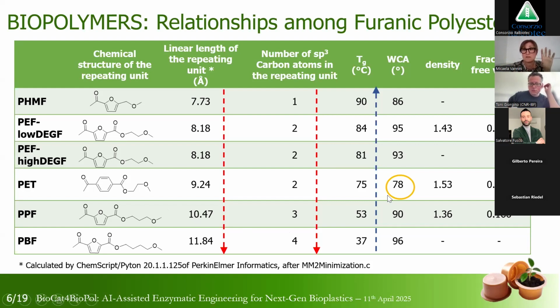If we consider the water contact angle for furan-based polyesters, we measured an angle higher than or equal to 90 degrees, because with these polymers, the ester groups are not completely available to interact with water. Some of these groups are already involved in other polar interactions, in particular with the furan ring.